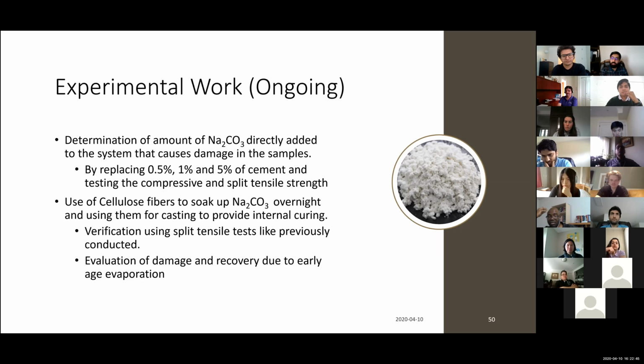Obina? You said the cellulose fibers don't like the alkali environment. Are you talking about the toughness added by the cellulose fiber, or something else? How is it damaged? It starts degrading. When calcium hydroxide or any alkaline solution is entrapped inside the lumen, which is inside the cell at the middle, it embrittles the fibrils. Okay, so the absorption capacity will be affected in that case. That's the damage, right?